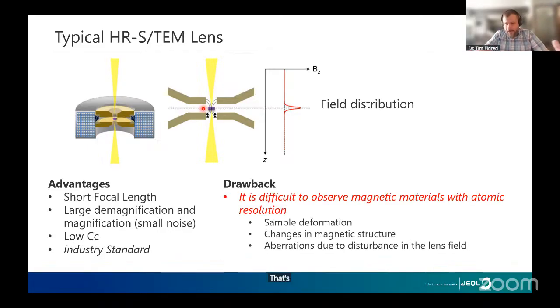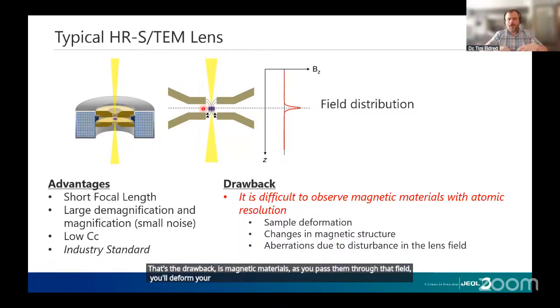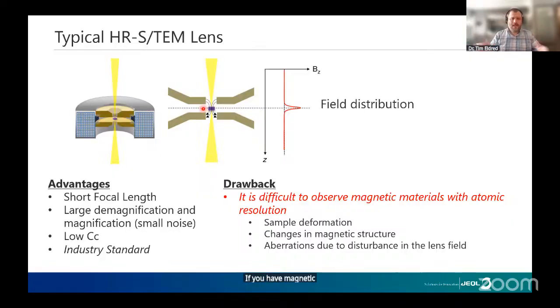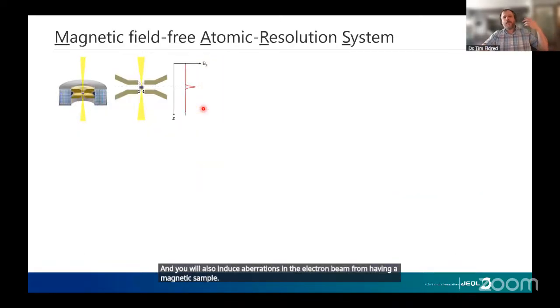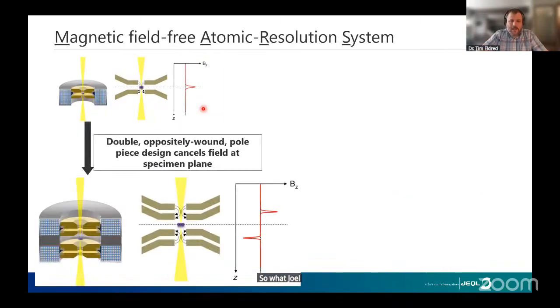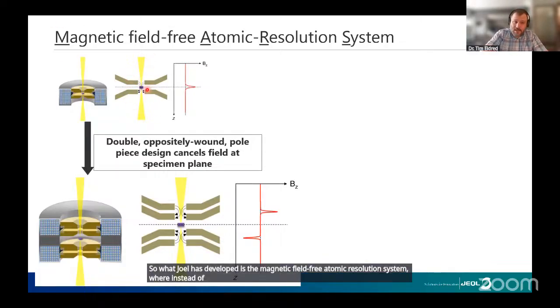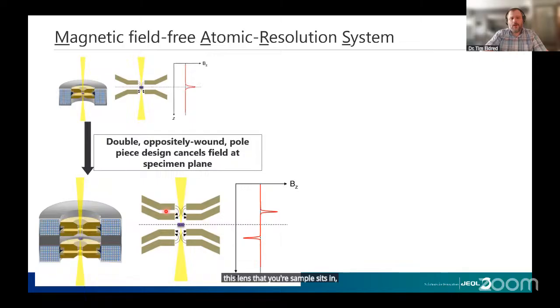That's the drawback: with magnetic materials, as you pass them through that field, you'll deform your sample. If you have magnetic domains, they will get swamped, they will get migrated, and you will also induce aberrations in the electron beam from having a magnetic sample. So what JEOL has developed is the magnetic field-free atomic resolution system, where instead of this lens that your sample sits in, there are 2 lenses above and below where the field cancels out.